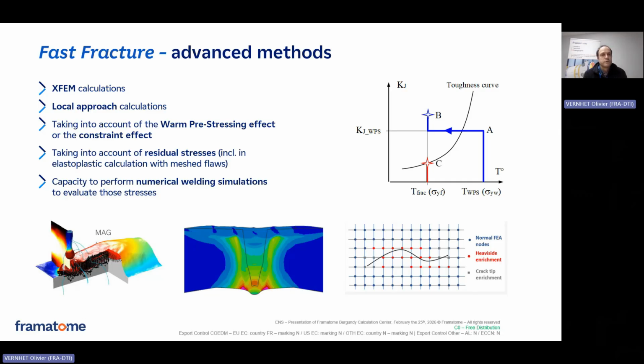We can also take into account some residual stresses, for example, residual stresses coming from welding. I said at the beginning that we can also perform some numerical welding simulations to evaluate those stresses and then take them into account in a fast fracture study with elastoplastic properties and a flaw mesh, for example.